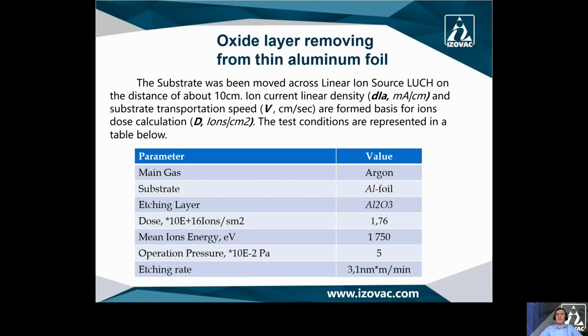Conditions are the same. Substrate was being moved across the linear ion source at a distance of about 10 cm. Ion current, linear density, and transportation speed formed the basis for ion dose calculation. The test conditions are represented in a table below. Argon as a main gas was used. Substrate, thin aluminum foil. Etching layer is aluminum oxide. Dose calculation value is indicated: mean ion energy, operation pressure, and etching rate. When you compare etching rate with ion dose, you can find a suitable solution for your application with different material when you know the sputtering coefficient of your material.